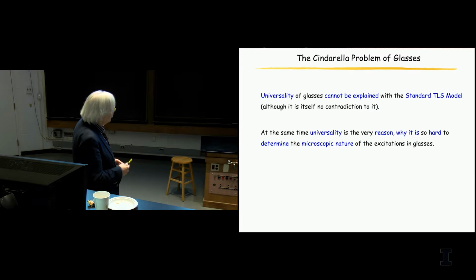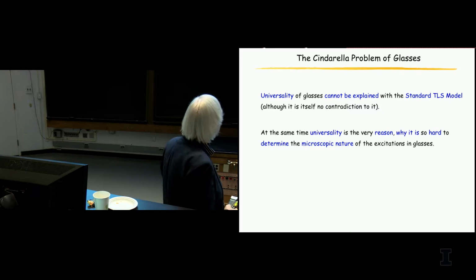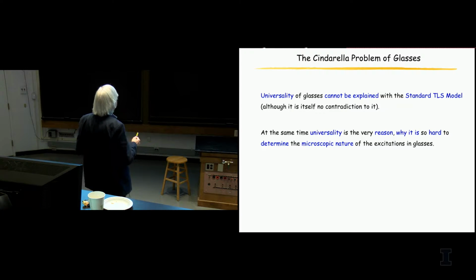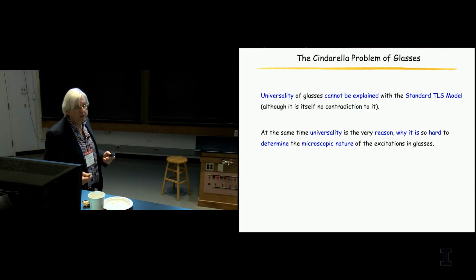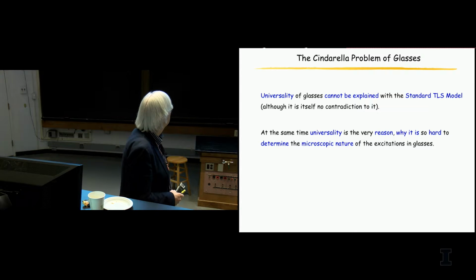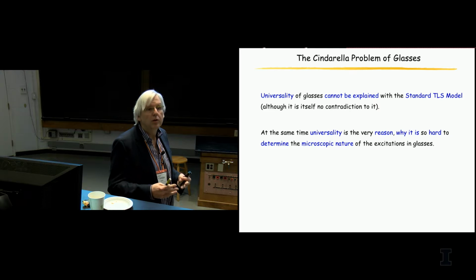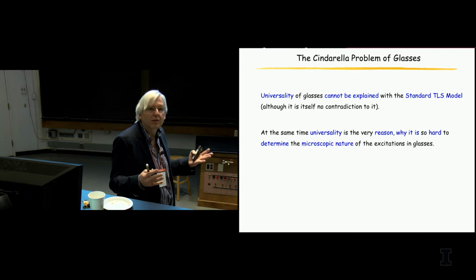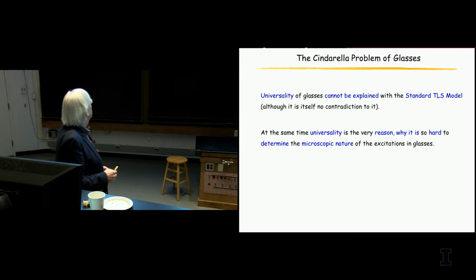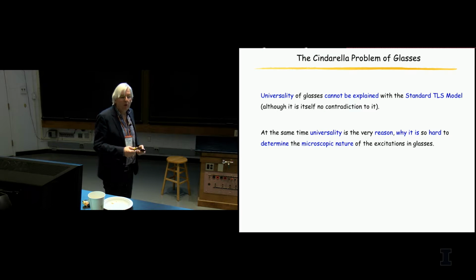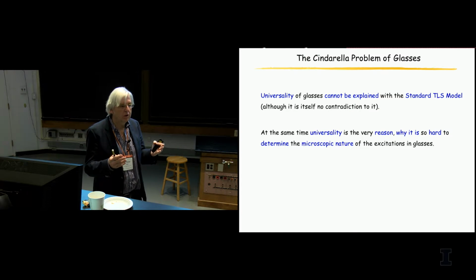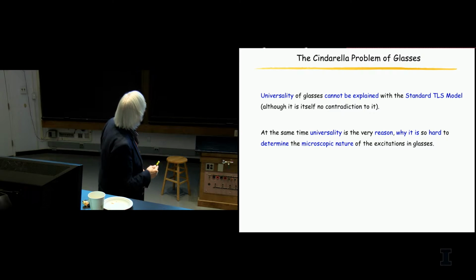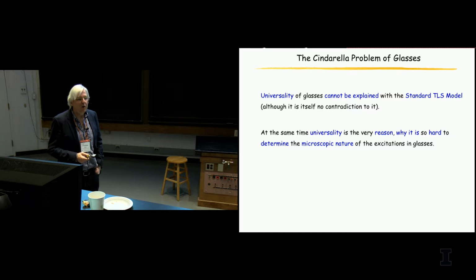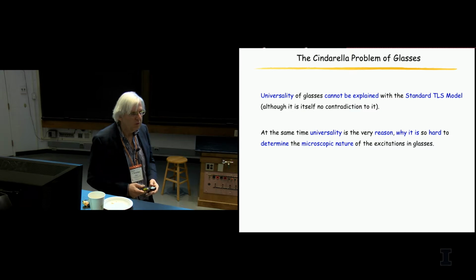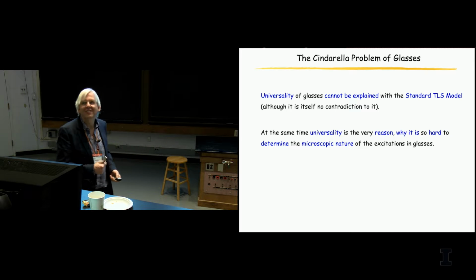Now, there's one intermediate slide I forgot. There are two things. The universality of glasses cannot be explained by the standard tunneling model that I already showed you, but it, of course, does not exclude the standard tunneling model. It would be a huge coincidence in some sense. But the universality generates the problem that we cannot really look for the microscopic nature of two-level systems, because no matter what we do to our glass, the experimental results are the same. So I found this term from Tony, the Cinderella problem of glasses. I think you used that in one of your Waterloo lectures. I found it very nice.